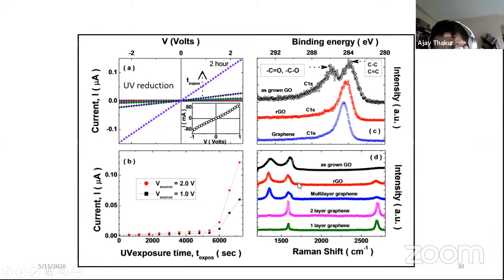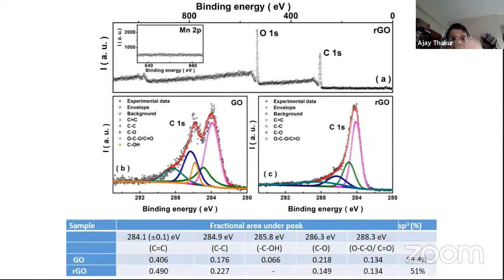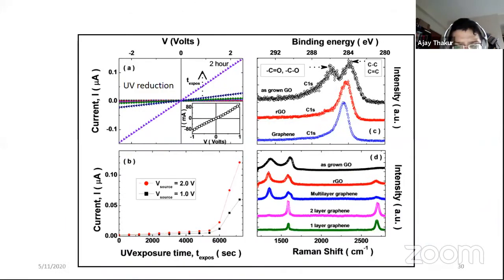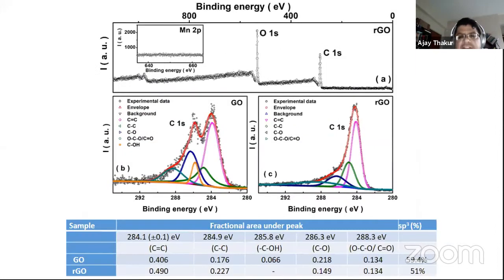And similarly, in the bottom panel, we show Raman spectra for a variety of samples, starting from as-grown GO to RGO to multi-layer graphene, 2-layer graphene, and 1-layer graphene. And this RGO is nominally reduced graphene oxide. So eventually we also reduced it to very high degrees, and we approached conditions closer to graphene nanoplatelets. Okay, so the IV characteristic, if time permits, if I have it in the slide, I would be showing.